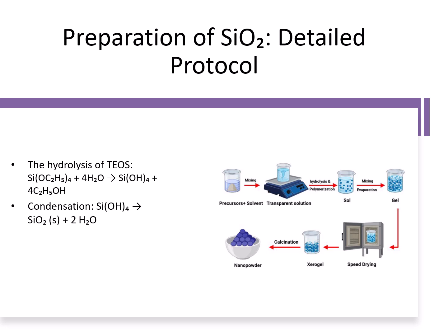In the sol-gel synthesis, tetraethyl orthosilicate is commonly used as a silicon precursor. The reaction typically occurs in a solvent mixture of ethanol and deionized water, with either hydrochloric acid or ammonium hydroxide as a catalyst to control pH. The hydrolysis step occurs at room temperature, around 25 to 40 degrees Celsius, where water molecules attack the bonds of tetraethyl orthosilicate to form silanol groups as shown in this equation.